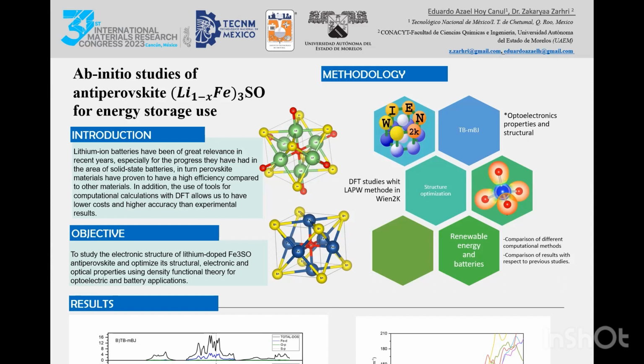For my methodology, use was made of the WIEN2k computational package within density functional theory (DFT) calculations. The Becke and Johnson potential modified by Tran and Blaha was used. In addition, unit cells were performed for Li3SO.